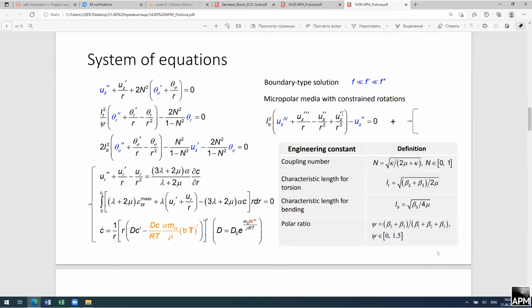And is your diffusion layer equal to the grain size? Yeah. We have obtained that it is about the grain size, but initially it was just some value in the equation. And finally, by comparison of the solution on the lateral surface with the solution inside the boundary layer, we obtained that yes, its length corresponds to the grain size.